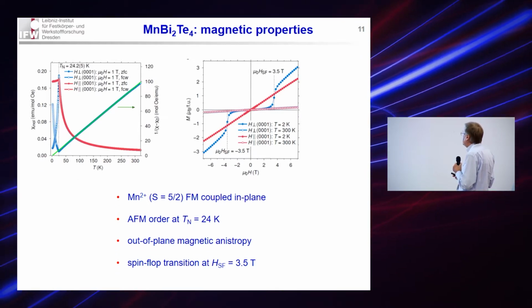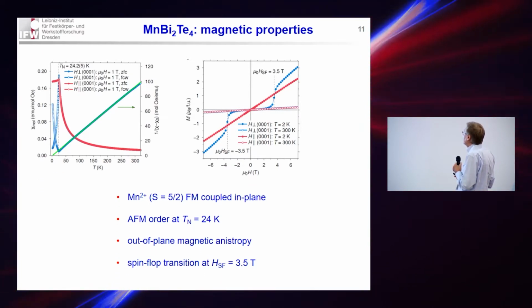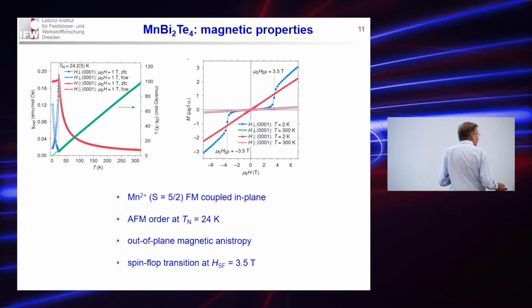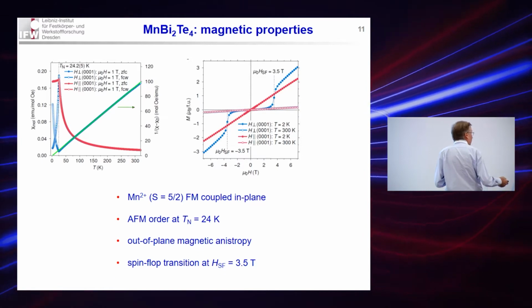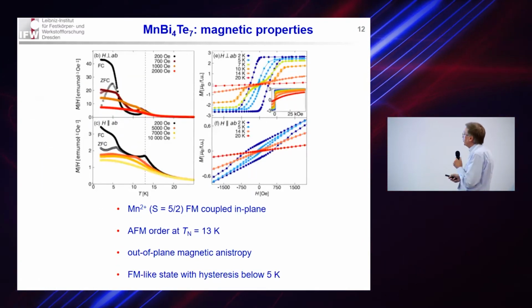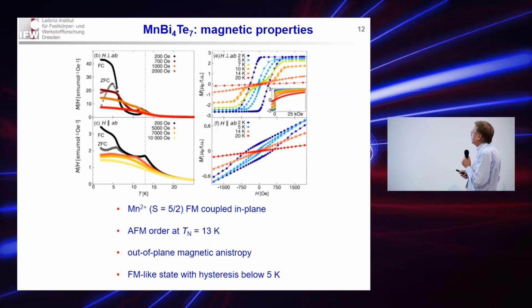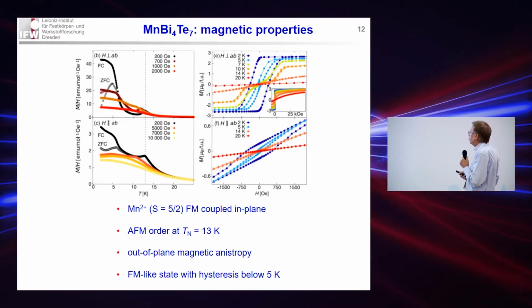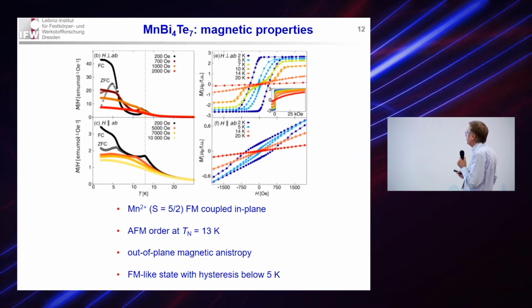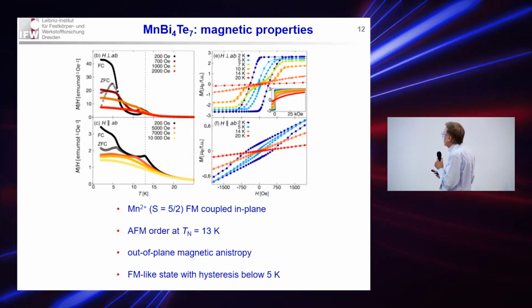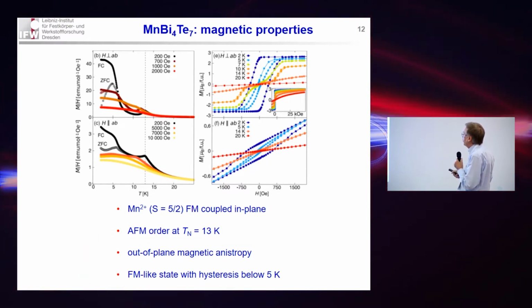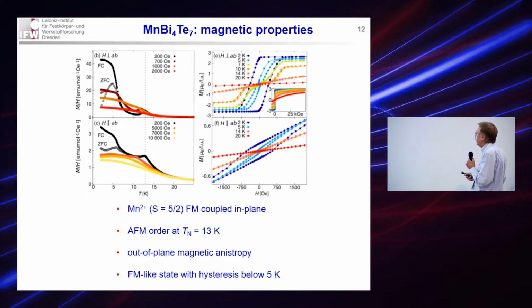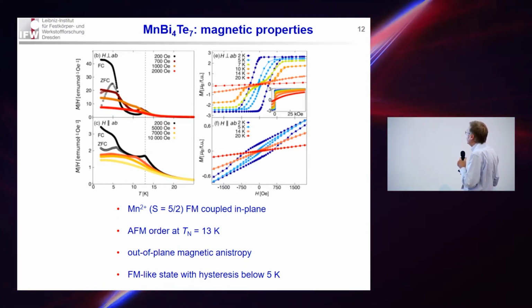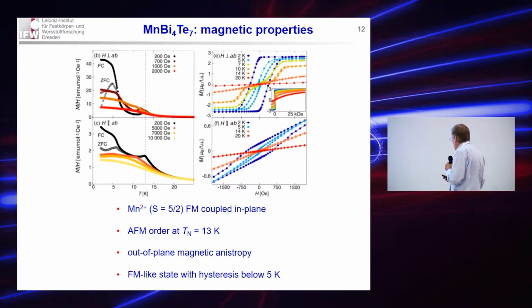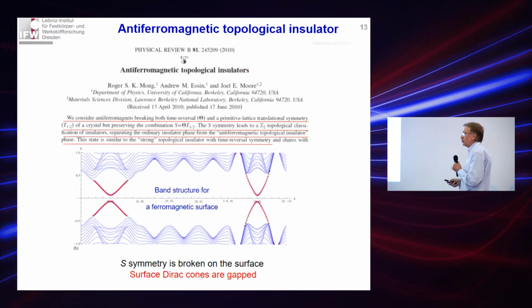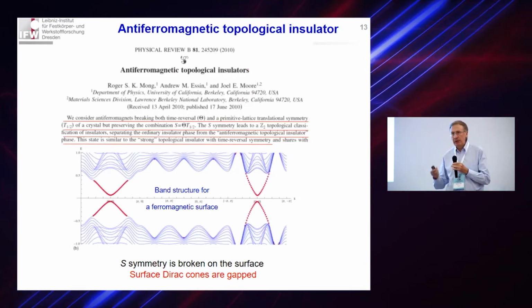A bit more complex situation takes place in 1-4-7. If one looks at the static magnetic susceptibility as a function of temperature, it also shows a peak at a temperature of about 13 Kelvin, indicating a transition to the antiferromagnetic ordered state. But at lower temperatures there is an increase of the magnetization, suggesting a kind of metamagnetic state, with hysteresis behavior of the magnetization. Actually, this is an antiferromagnet, not a desired ferromagnet, but an antiferromagnet.